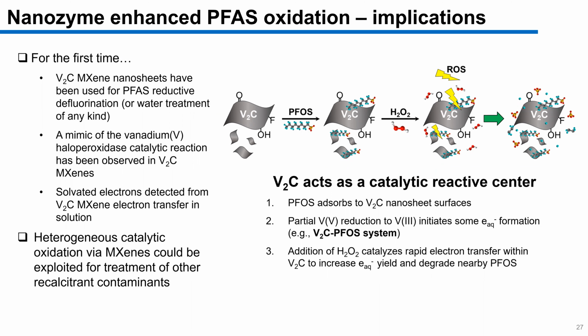Yep, good question. So vanadium, I can't recall the MCL for vanadium in water, but yes, to a certain degree, vanadium can be toxic if you are exposed to it or ingest it in water. However, we are using very small doses of these vanadium carbide materials to degrade PFAS, so much lower than levels where you would start to exhibit toxicity to either humans or aquatic life if you were to discharge this PFAS treated water that may have residual vanadium species in the discharge water.